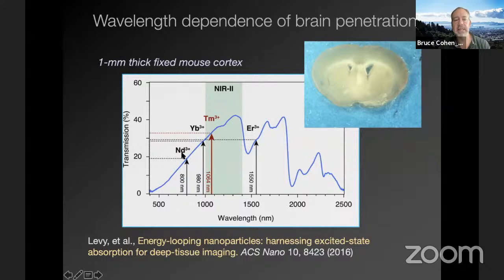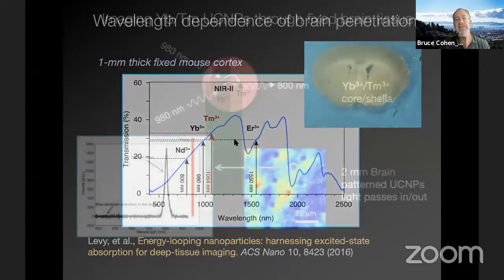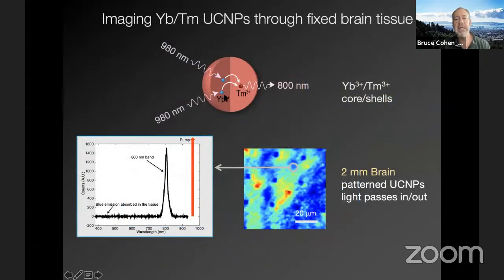And these are the sorts of lanthanides that we use interchangeably to dope into our nanocrystals. What we showed initially was you can take this combination, ytterbium and thulium. The way our upconversion typically works is you have something that absorbs the light and passes it on through a resonant energy mechanism to a neighboring lanthanide in the nanocrystal matrix. That happens multiple times, sequentially, and that's how you get upconversion. So here you can absorb at 980, where ytterbium absorbs very well, and get emission from thulium at 800. And you can see that through 2 millimeters of mouse brain.